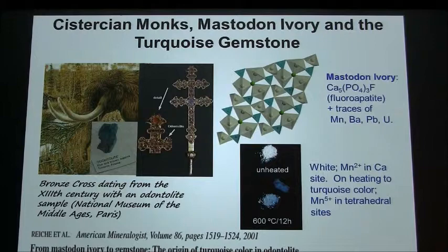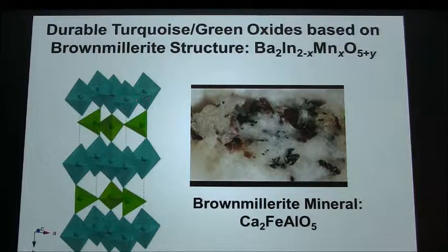Why not? So we choose a structure which is very similar to that of calcium apatite, containing tetrahedra and octahedra, just like calcium apatite. But I know how to make this because I have worked on it before. We call it brownmillerite, named after the discoverer of a mineral which contains octahedra and tetrahedra, and it's very highly stable.